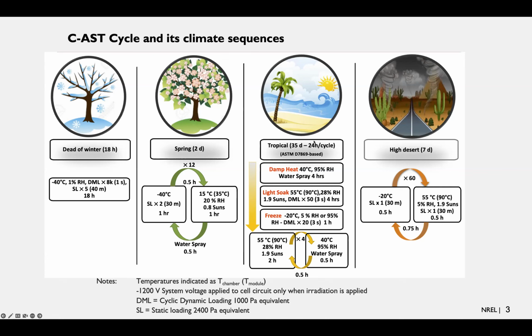Then there's a tropical, and this is the first one we applied, and it's from ASTM D7869. When I say first we applied, we started combined accelerated stress testing with this particular cycle, but it's evolved to include all four that we're looking at here. It's the longest, and it involves a damp heat sequence, a light soak sequence, a quick low temperature sequence, and then basically a set of sun showers alternating between sunlight and water spray.